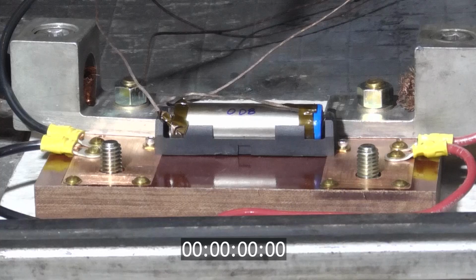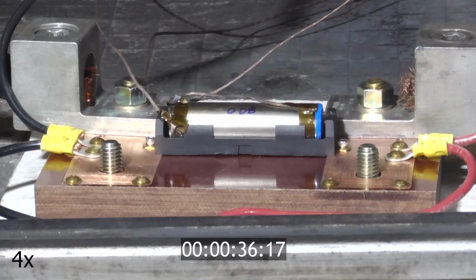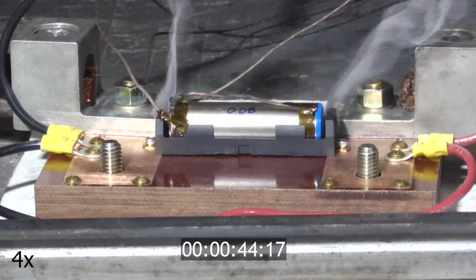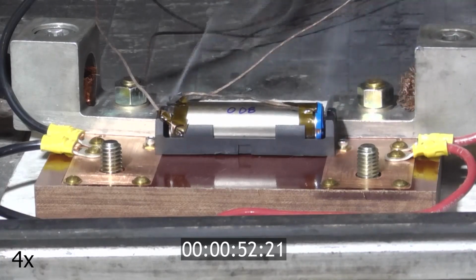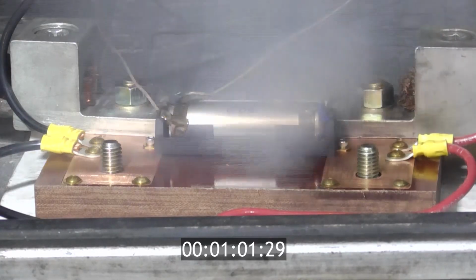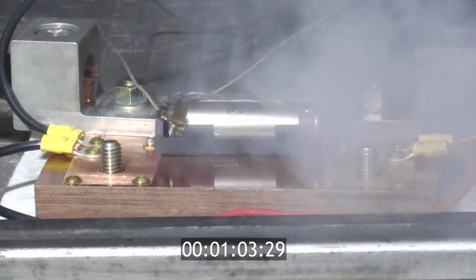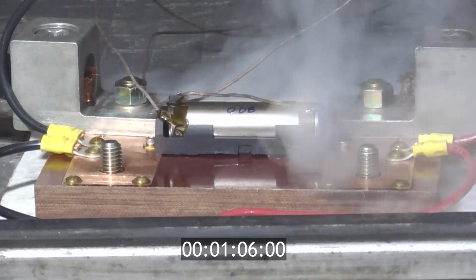Normally for external shorts, we don't see a whole lot. So it was a little surprising to actually get a vent, a diffused vent in this external short. So at first you'll hear a loud sound. It's the external contactors closing. You will see a little bit of smoke that's from the fixturing getting too hot, but then you'll hear an audible pop that's from the vent itself. And then if you look below the fixture at the vent, you'll see some leaked electrolyte.